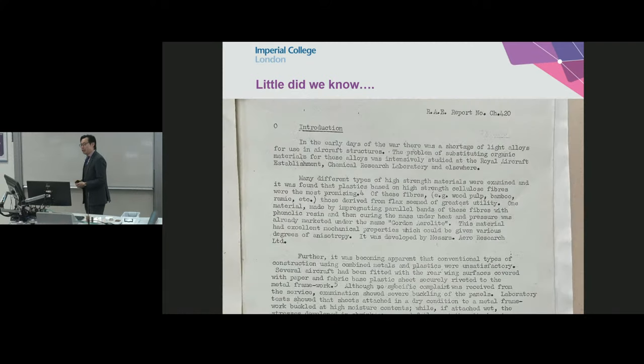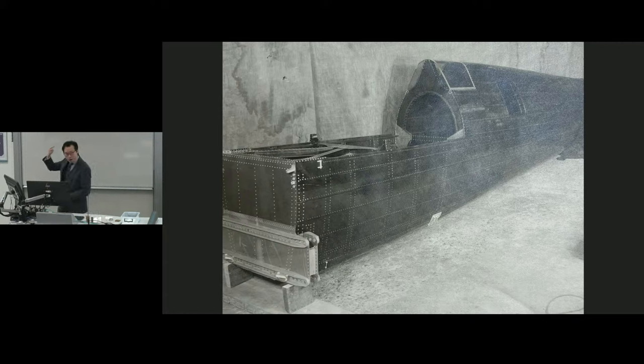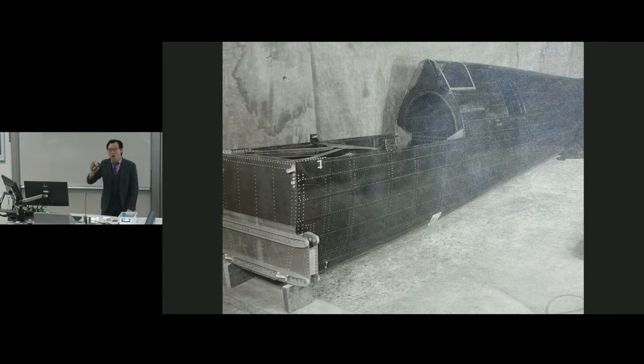Within that document, it highlighted that during the early days of the war, again, the Second World War, there was a shortage of lightweight alloys. And the RAE, the Royal Aircraft Establishment, tried and tested a lot of different materials to replace those lightweight alloys, and one of which, plastics based on high-strength cellulose fibers, was the most promising. They did not stop there. They didn't build little tiny test panels. They actually built a prototype of a Spitfire out of this cellulose fiber reinforced phenolic resin. That Gordon Aerolite is essentially flax fibers, so plant fibers, impregnated with phenolic resin. They molded it, they built a Spitfire out of it. Luckily, the war ended, so it did not need to go to production. Luckily, thank God for that.